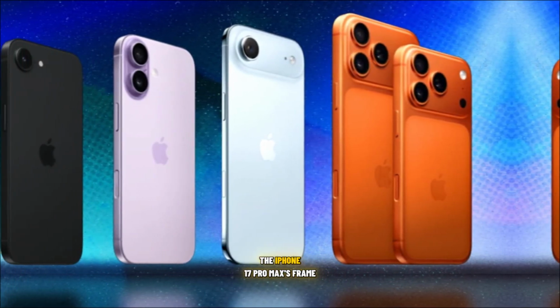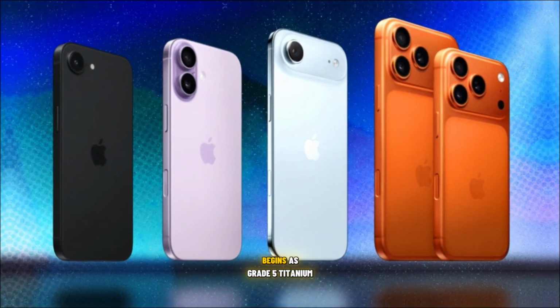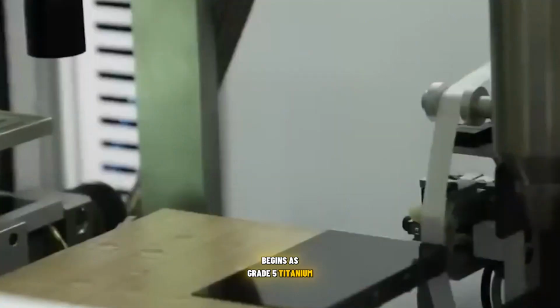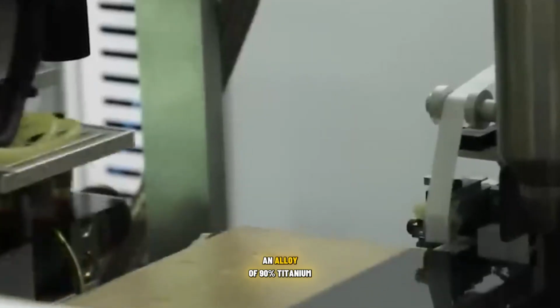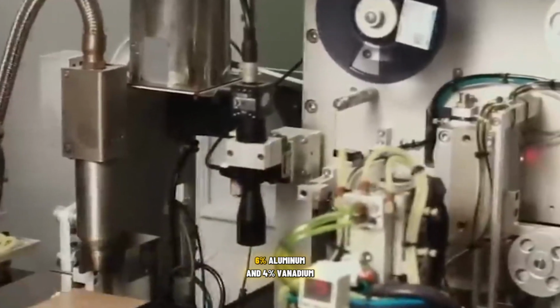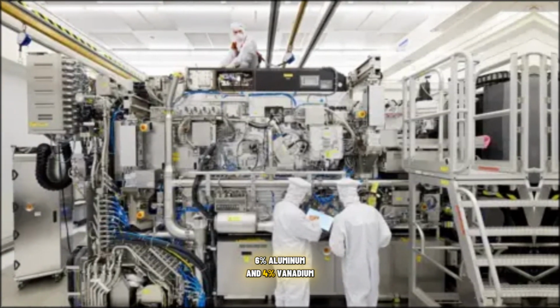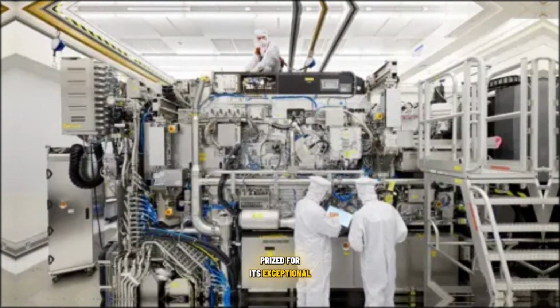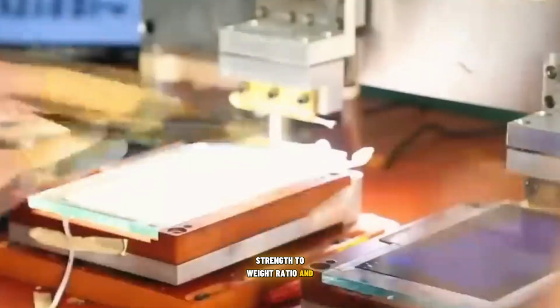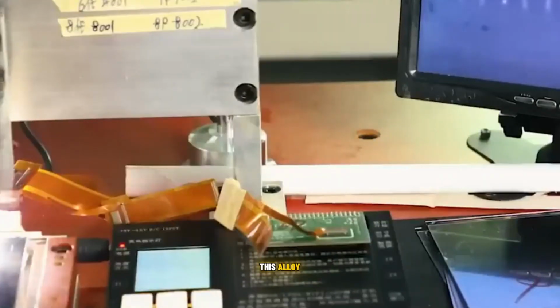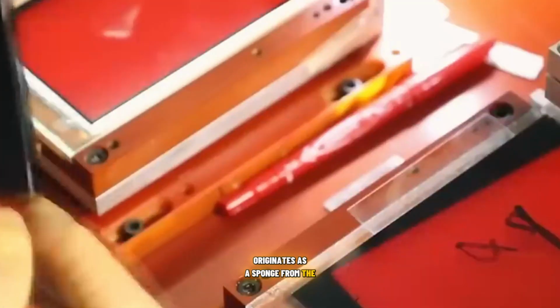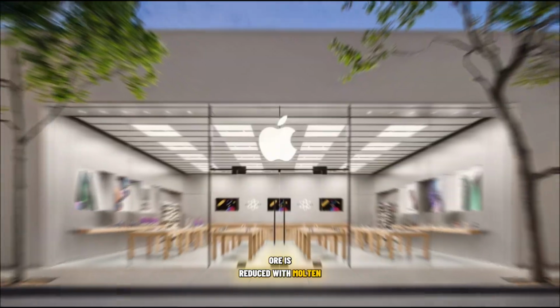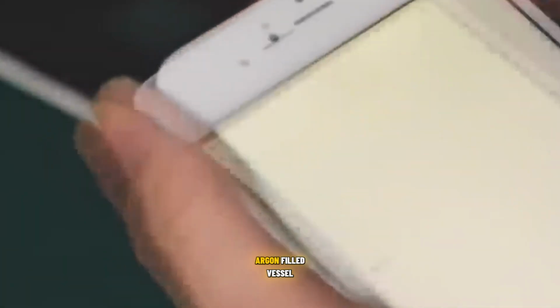metal. The iPhone 17 Pro Max's frame begins as grade 5 titanium, Ti6Al4V, an alloy of 90% titanium, 6% aluminum, and 4% vanadium, prized for its exceptional strength-to-weight ratio and corrosion resistance. This alloy originates as a sponge from the Kroll process, where titanium tetrachloride, itself derived from rutile ore, is reduced with molten magnesium in a sealed, argon-filled vessel.